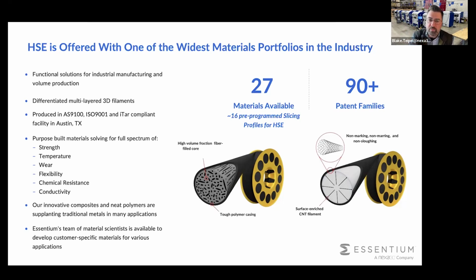Many of our high-spec materials, both the high-spec carbon fiber materials and the ESD safe materials, use multi-walled carbon nanotubes. We put these into a polymer master batch. We let them down to very, very low concentrations, less than 1 gram per kilogram, which is less than 0.1%. But we get clean room safe, consistent ESD properties because it's a nanomaterial concentration that has been nicely dispersed and yet fully encased in a polymer master batch. So you don't have to worry about nanotubes flying around, getting in the air.